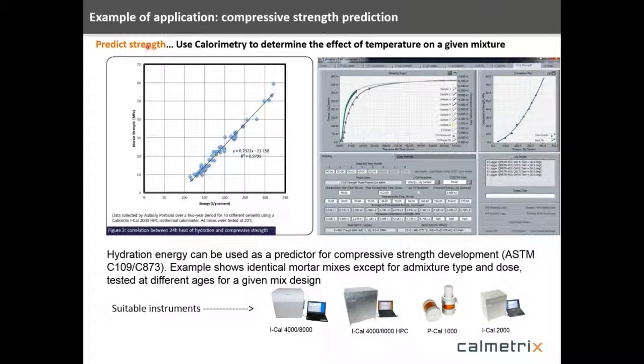Now another great example is the use of isothermal devices for predicting compressive strength. And if you recall back on one of the earlier slides, we talked about the fact that the area under that curve, the integration, the joules per gram, is related to the compressive strength. So we use that relationship between the energy, the joules per gram, and the strength that gets built up within the concrete, in order to predict compressive strength.